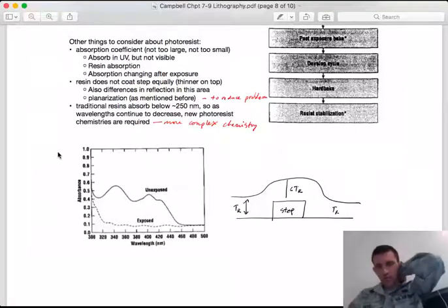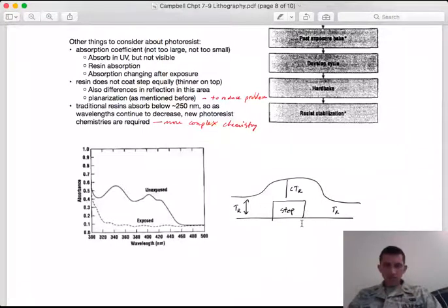If you have a step, say for instance like this sketch here, you're going to have a thickness of your photoresist on top of the step and across the corner that is less than what you get on the fields, right? If you've ever painted something with sharp corners, you know that the paint layer is thinner at the corner than it is on the flat. Same thing happens here with the spin coating.